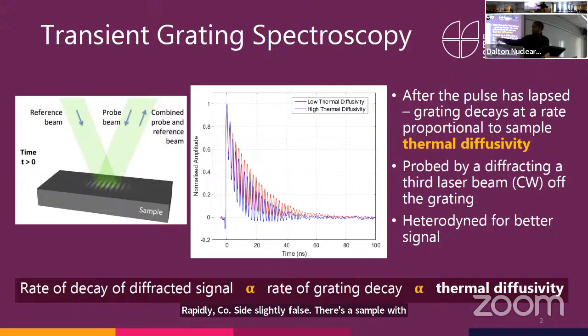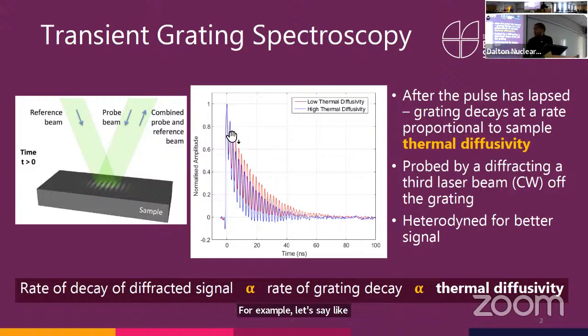So these are two samples of tungsten that differed slightly in terms of their thermal diffusivity. But for example, a sample of implanted silicon carbide would decay over an order of magnitude longer in time. And so the rate of decay of the diffracted signal is proportional to the rate of the decay of your grating, which is proportional to the thermal diffusivity.